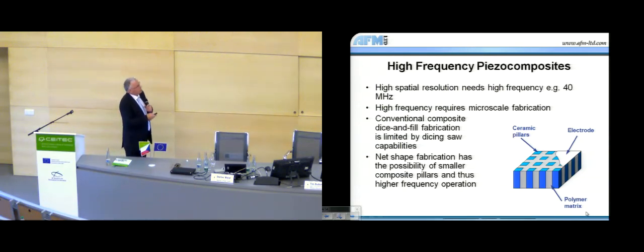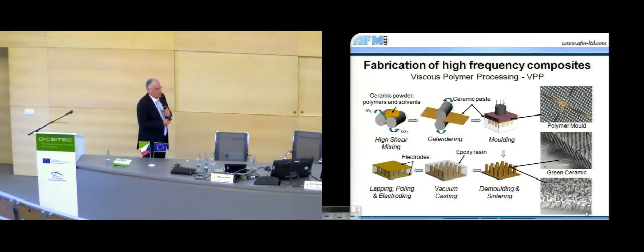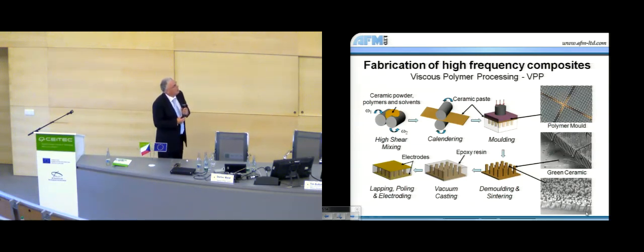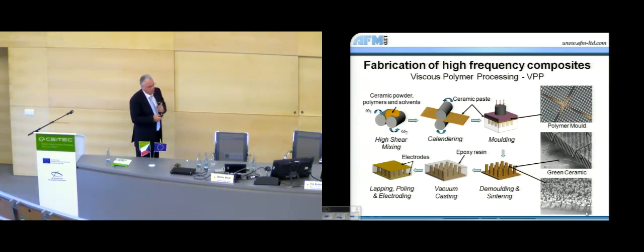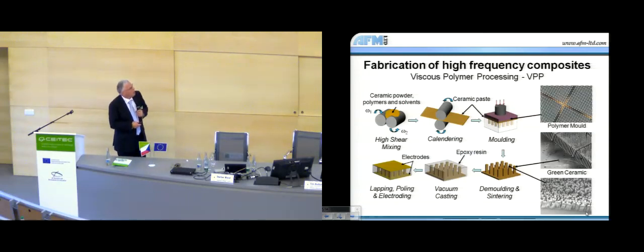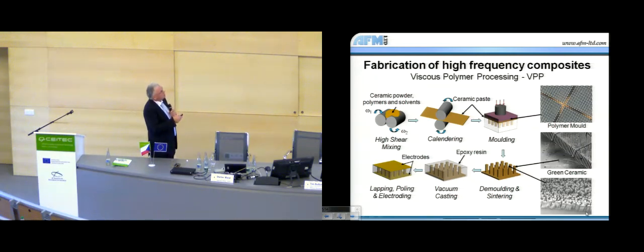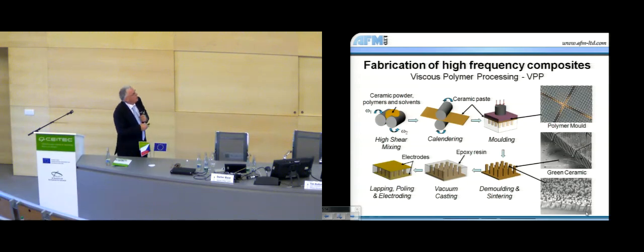And so what we've developed is a molding technology. So this comes back to one of the areas that you saw at the beginning of my research career. One of the net shape things that we've been able to do. So we start with a powder. We mix it in some way. We mold it into a mold. We then demold and sinter. We end up with these sort of pillar structures, which we then encapsulate and then lap and polish and put electrodes on. And there is our device.